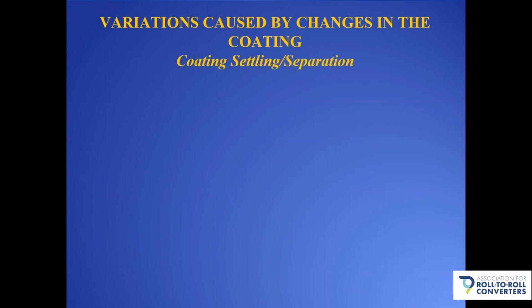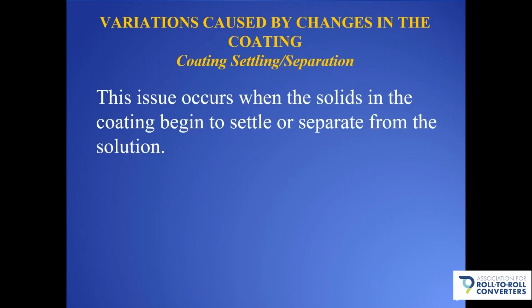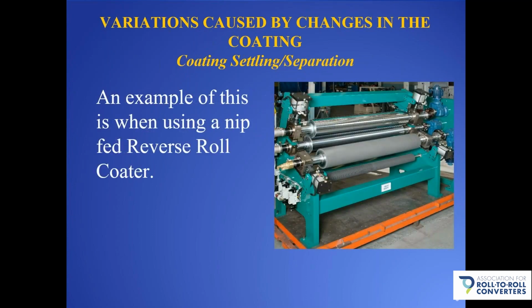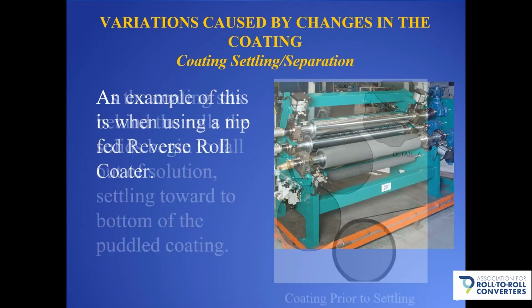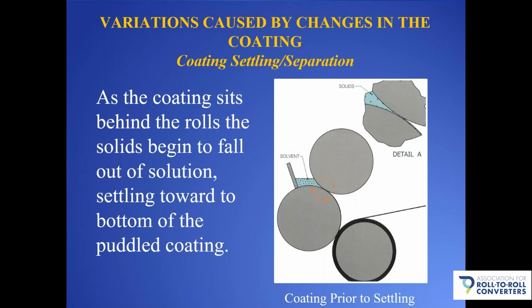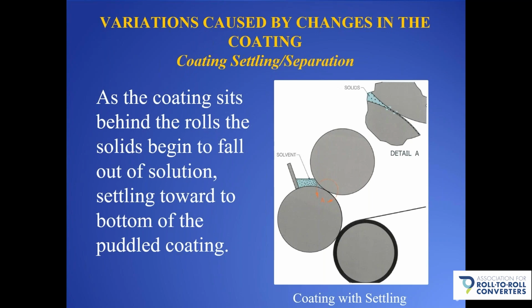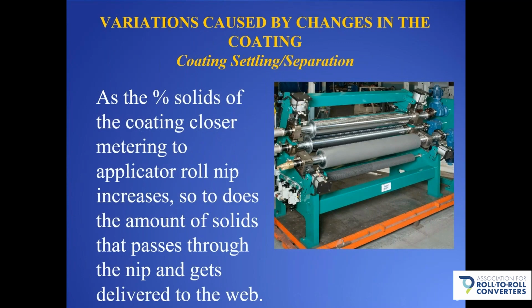Next, let's talk about coating settling and separation. This issue occurs when the solids in the coating begin to settle or separate from the solution that's holding them. As an example, let's look at a nip-fed reverse roll coater. As the coating sits behind the rolls, the solids begin to fall out of solution, settling toward the bottom of the puddled coating. So in this sketch, you see at the beginning a fairly even or uniform distribution of the solids. And in time, the solids begin to migrate toward the bottom of the puddle or pond. As the percent solids of the coating closer to the metering to applicator roll nip increases, so too does the amount of solids that actually passes through the nip and gets delivered to the web.